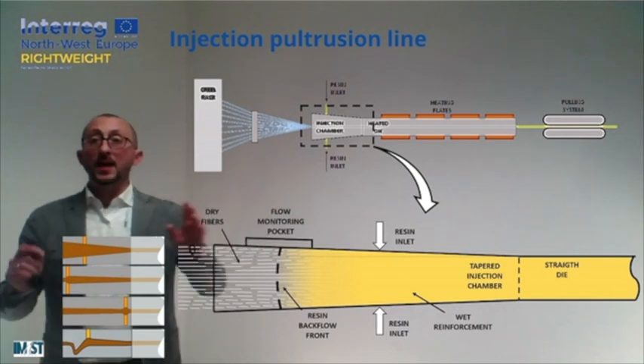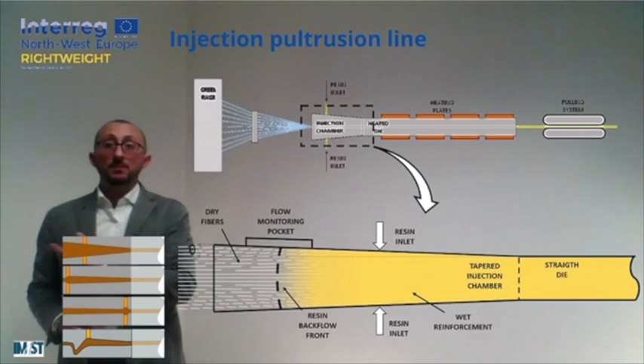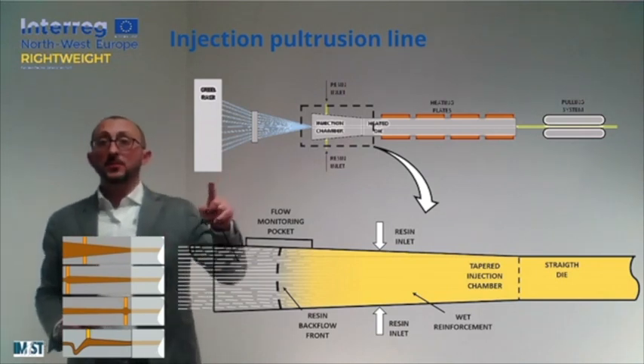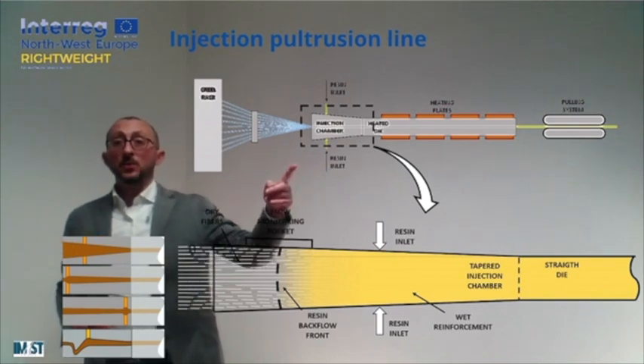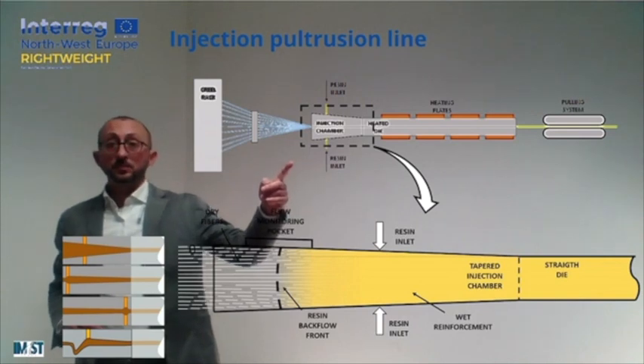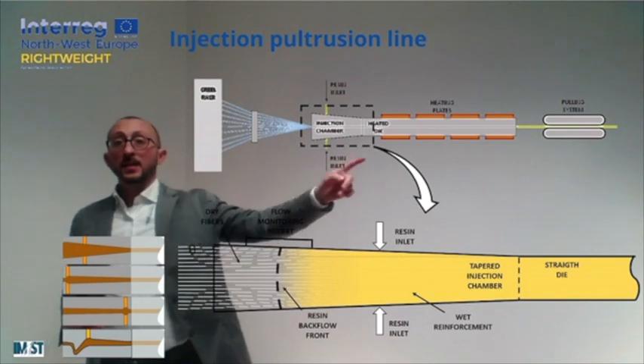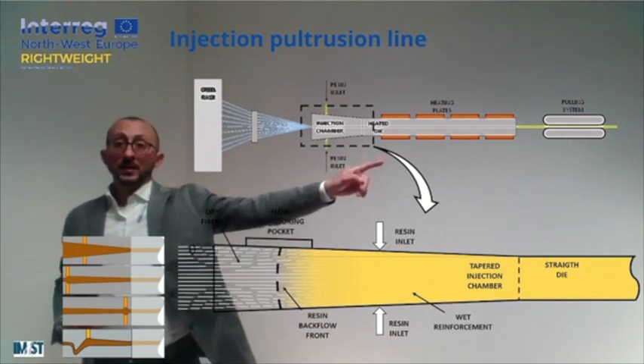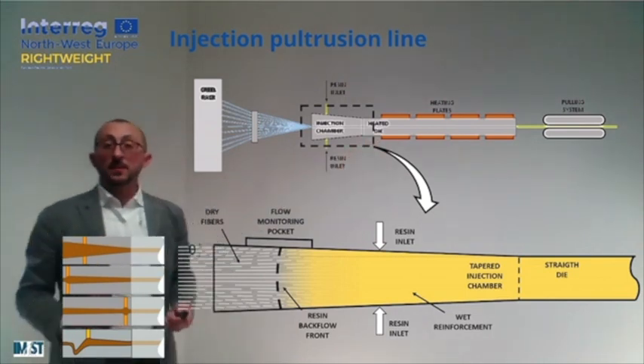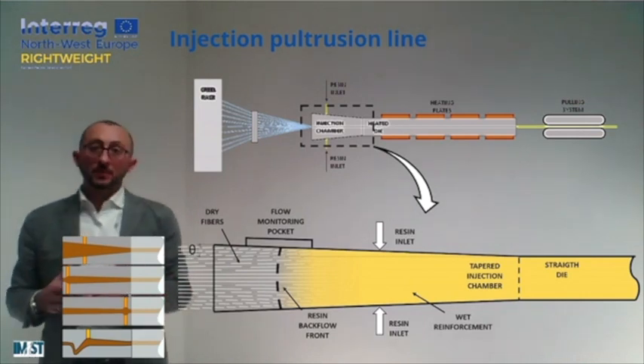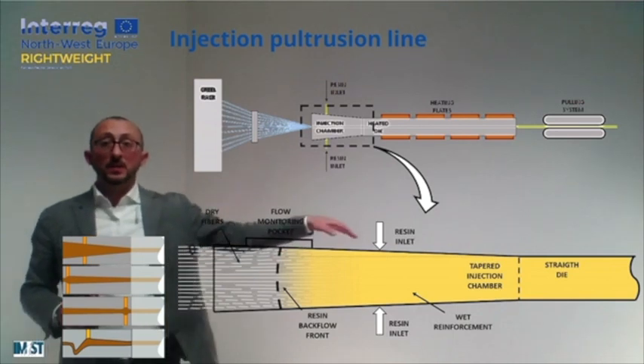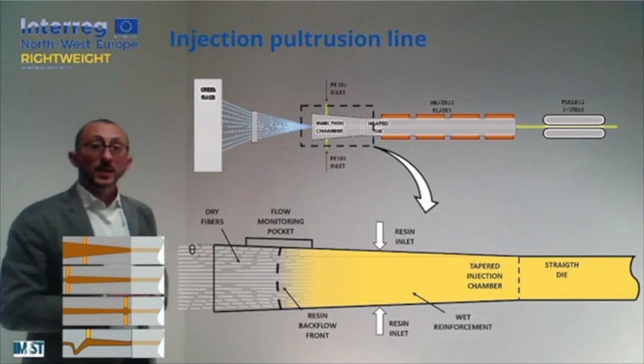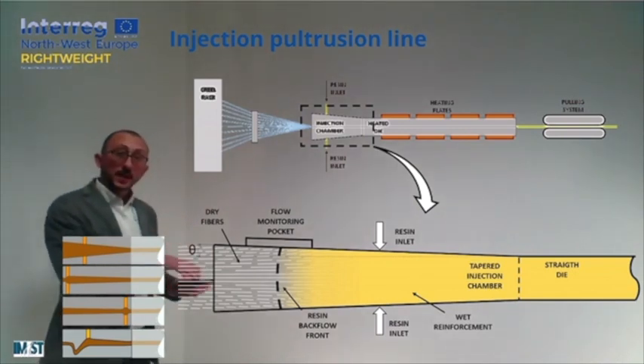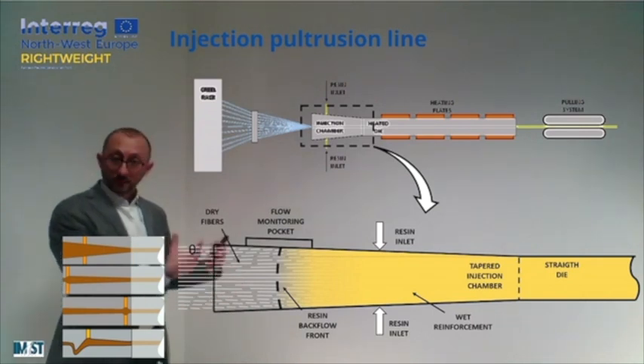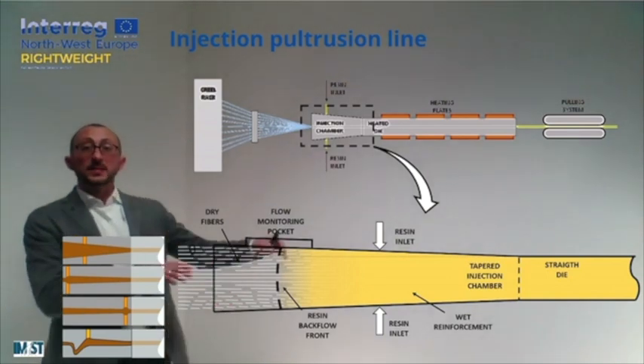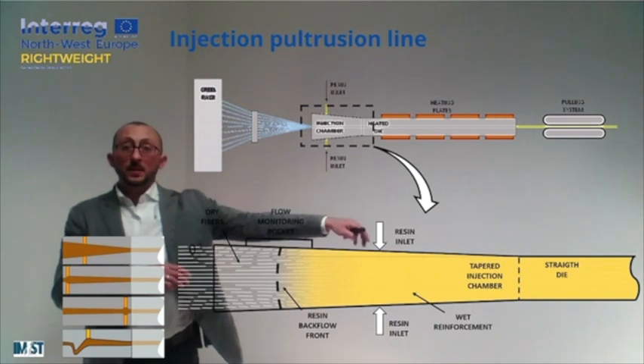And as you can see, more or less the same stations that we were looking at before are there. So the creel rack, some preforming, but instead of the open bath, what we have here is an injection chamber. And typically this injection chamber is directly connected to the heating and curing die. So the rest of the line is pretty much the same, which is the idea behind this injection chamber. Actually, the internal part of the cavity is represented down here. So we can imagine that the dry reinforcement is directly going inside this chamber after the preforming step, and at some point of the chamber, the resin can be injected.